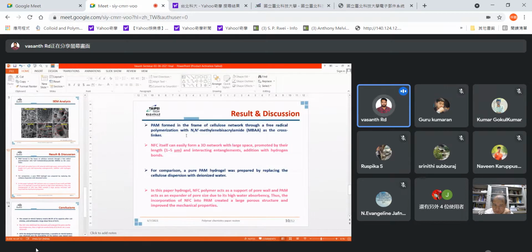And the resultant discussion: a PAM formed in the frame of cellulose network through a free radical polymerization with N-methylene bis acrylamide as the cross linker. The NFC itself can easily form a 3D network with large space promoted by the length of 1 to 5 micrometer and interacting entanglements in addition with the hydrogen bonds.